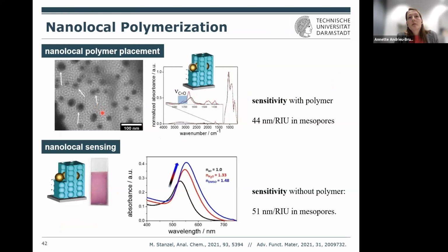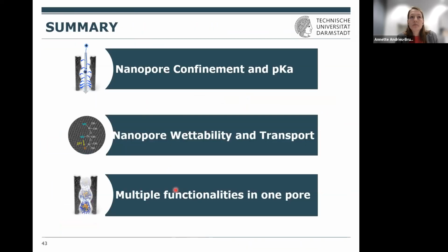And this is just to show you the results for the nanoparticle system. You see in TEM that there is a kind of corona evolving if you do this. You can, of course, analyze the plasmon band and estimate a kind of sensitivity from the UV-Vis spectra, but as well, this shows increasing refractive index, which as well indicates that there is polymer formation.